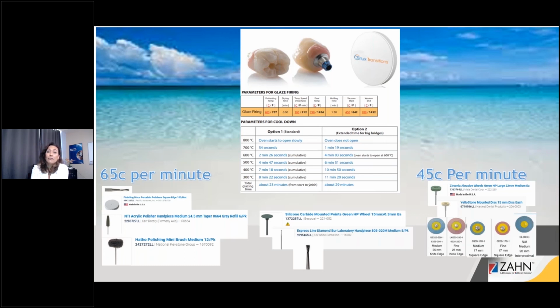And then always, if you've ground on zirconia, you want to make sure that you are rubber wheeling it for two reasons. If you rubber wheel it and then lightly sandblast it, you'll get a fantastic glaze in the end. You'll only have to glaze it once. You won't have to do it twice. And you especially won't have to do it twice if the zirconia you're using is already shade accurate. You won't have to do a second firing to perfect the shade. And also because we all know that stain and glaze wears away eventually. And so rough zirconia in the patient's mouth is not a good thing. We're going to cause them trauma to their opposing dentition. And obviously we don't want to do that. So zirconia is a very friendly material to opposing dentition as long as it is polished.